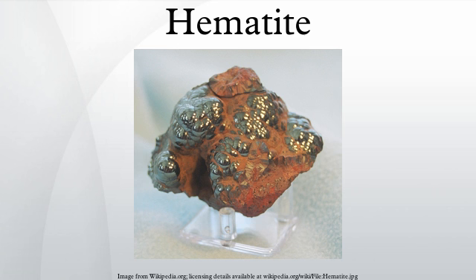Because terrestrial hematite is typically a mineral formed in aqueous environments or by aqueous alteration, this detection was scientifically interesting enough that the second of the two Mars exploration rovers was sent to a site in the Terra Meridiani region designated Meridiani Planum. In situ investigations by the Opportunity rover showed a significant amount of hematite, much of it in the form of small spherules that were informally named blueberries by the science team. Analysis indicates that these spherules are apparently concretions formed from a water solution.